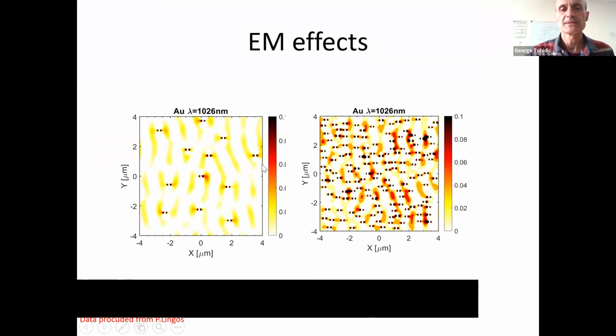No. Simulations and also the experiment show that it does not matter how many defects. I mean, the corrugation pattern does not influence a lot. You see here, with some defects and with a bigger number of defects. So you see these black dots, and you see here a smaller number of dots. More or less, you get a similar profile.